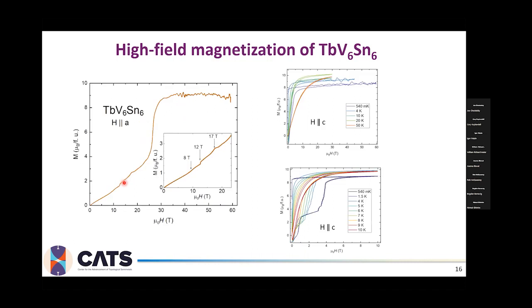As we look at the magnetic field applied along the C direction, it was already shown earlier that it has a very sharp transition in the low field and then stays saturated up to 60 Tesla. However, what we noticed and was not previously reported is that at low field and very low temperature, there is a very huge hysteresis. We can also see that there is a plateau which exists around 1/3 towards the saturation. And also there is a huge diamagnetic signal at very low field.